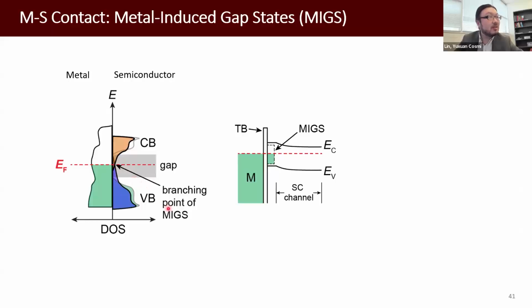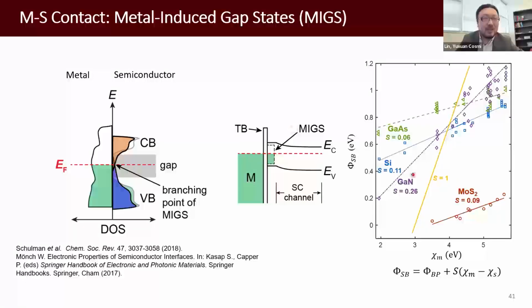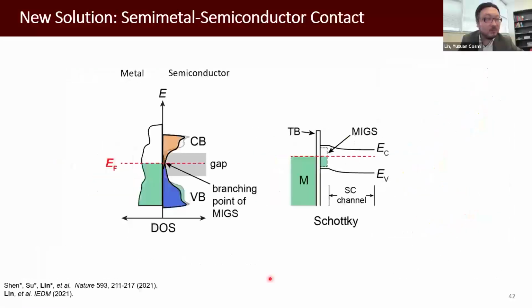As a result, within the band gap, there are additional states generated. We call them metal-induced gap states, or MIGS. When we put these two materials in contact, electrons have to fill those MIGS. If we have enough electrons, they may go to the conduction band. But in most cases, we don't have enough electrons. Then the Fermi level will be pinned in the middle of the band gap. When we consider that for all different semiconductor materials, this modulation is much weaker. The slope is much, much smaller than 1.